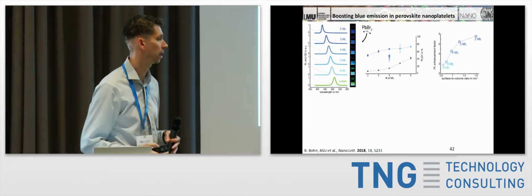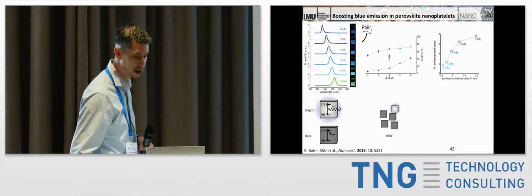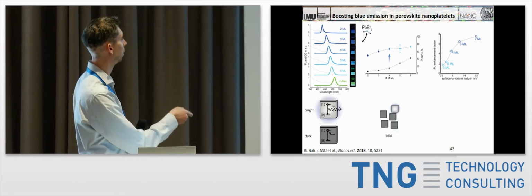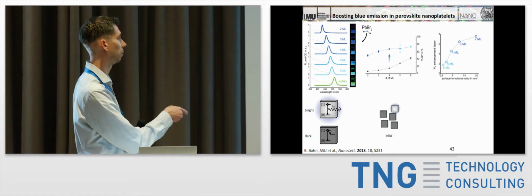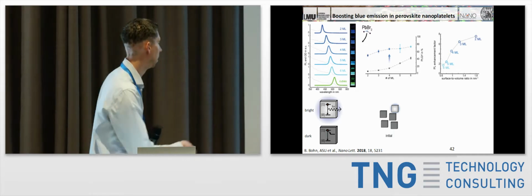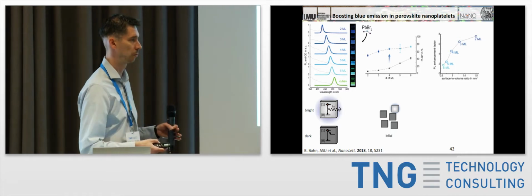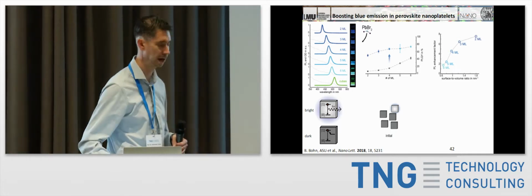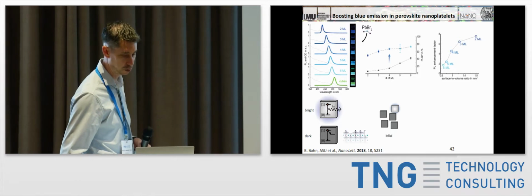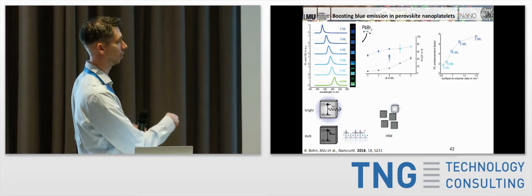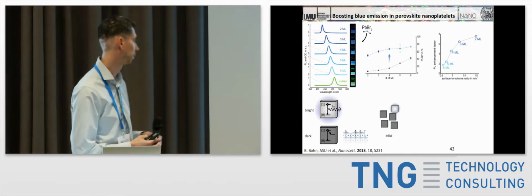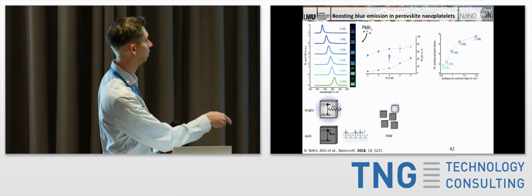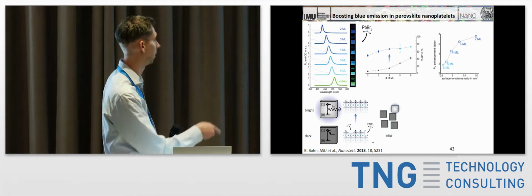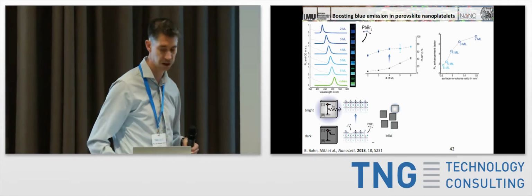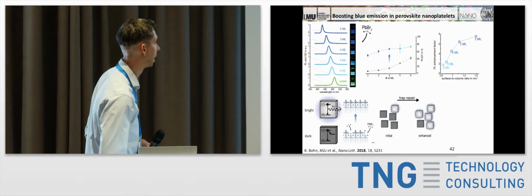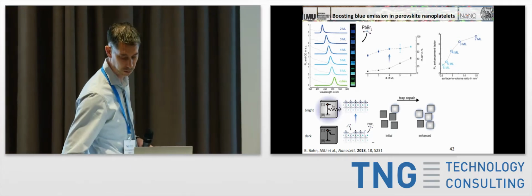So we immediately thought of the idea, okay, this has to have something to do with the surfaces that we have in there. And so essentially what we're saying is that at the beginning we have some platelets that absorb light and make photons. These are bright platelets. We have a lot of dark ones that absorb light, but basically the light is trapped. It can't come out of that again. And what this lead bromide is doing is essentially, in these dark platelets, we have a lot of imperfect crystals there, and it's basically filling out these holes that we have in there, filling out the crystals so that they then turn into nice, fully passivated crystals, and that's then turning a lot of these dark platelets on again, so that they now are able to emit light efficiently.